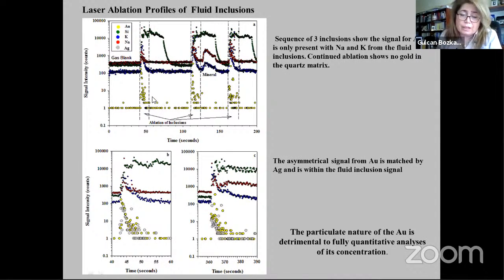Here we show the ablation profiles. All contain gold and silver, and these are only recorded when the sodium-potassium peaks from the fluid inclusion solution are present. There is no gold or silver in the quartz, as you can see here, but we continue to ablate. A noticeable feature is that the gold and silver signal is spiky, indicating particles, in contrast to sodium and potassium, which is smooth and asymmetric.